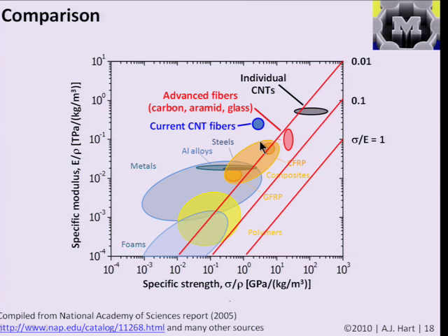If we look at this chart and plot lines of constant values of sigma divided by modulus, here strength divided by modulus, you can see that our theoretical limit of 0.1 is not approached within an order of magnitude by many of these materials. In fact, measurements of individual nanostructures, individual nanotubes, show a lot of variation, and we'll see the origin of that later. But there we can almost get to this theoretical limit, where some researchers have measured carbon nanotubes that fail at a tensile stress of 100 GPa, or 0.1 TPa, terapascals, which is 1/10 of the